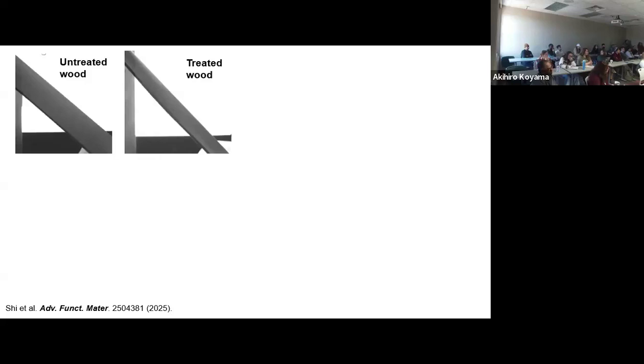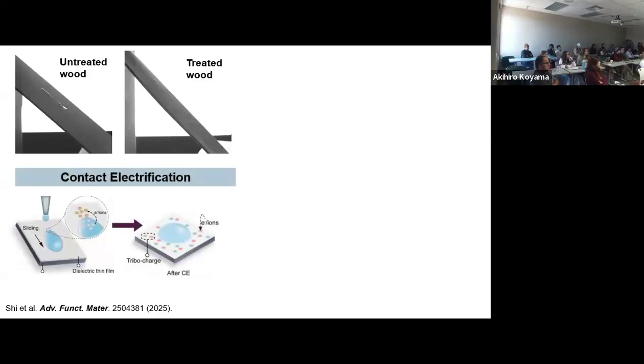You can read the details here. The fact is that if you have untreated wood, water will fall, will stick, right? Because wood, unless it's treated, is quite wettable, right? But the treated wood that we made by this lignin relocation shows a different behavior because it's fully repellent to water, the water falls and then rolls, right? And this can be used not only to protect the house, but also to produce contact electrification. So this is a little fancy extra step where the sliding droplets locally generate charges, and that leads to something called contact electrification. When you put solids in contact, you generate electricity.